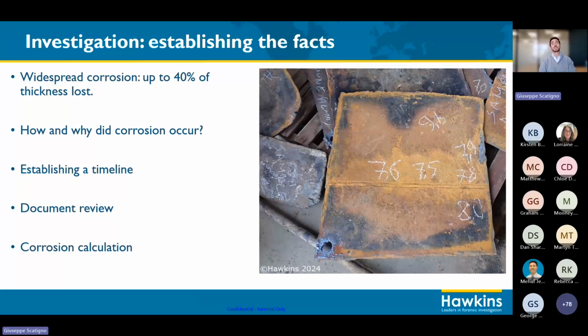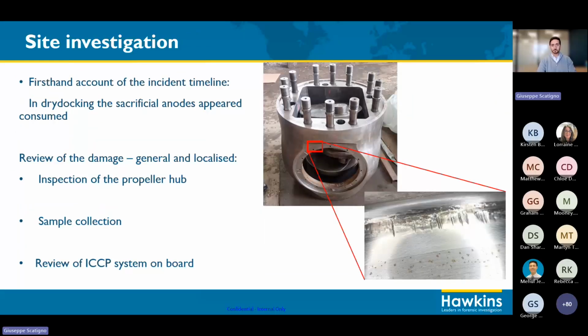So that is a significant amount of corrosion, and one that we do not normally see on a vessel that is well protected. It was important to try and establish a timeline to understand exactly when last time a survey was carried, in order to understand how corrosion could have evolved and with what speed. So I received a number of documents from the owner and from the insurance that allow me to look more into these details. And as part of the site investigation, I also looked at other components that suffer significantly.